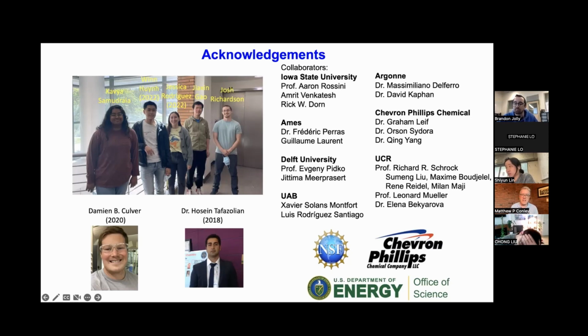With respect to silanes on surfaces, I didn't really talk about that, but if you engineer flexible linkers that contain ligands that can bind to your metal, you can still get dimers even if you try to promote very low surface coverage of the ligand. That was a bit surprising to me, but I think Christoph Copéret just published a paper on that recently, looking at some palladium NHC systems that I was also involved with as a postdoc, where we had originally thought that these were single site palladium NHC systems, but then using more advanced NMR spectroscopy, it looks like there's a significant contaminant of bis NHC palladium species. So with those, you have to be a bit more careful, to make a long story short.